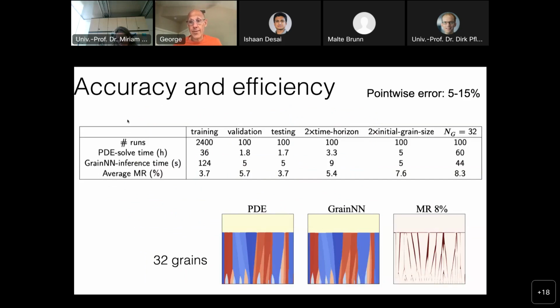So just to show you the overall cost, the 8-grain training, as I said, takes 2,400 8-grain phase field simulations. It takes 36 hours to run on a single A100 GPU, and the inference for all 2400 takes 124 seconds once it's trained, and the average error is about 4%. In the validation test, in which we use basically to tune hyperparameters, we get about 6% error. We use only 100 simulations, 1.8 hours and 5 seconds for the neural network. In the testing, similar numbers.